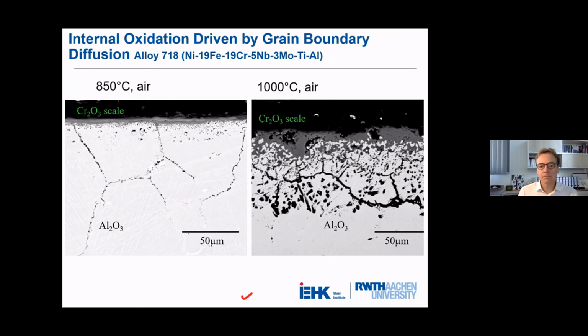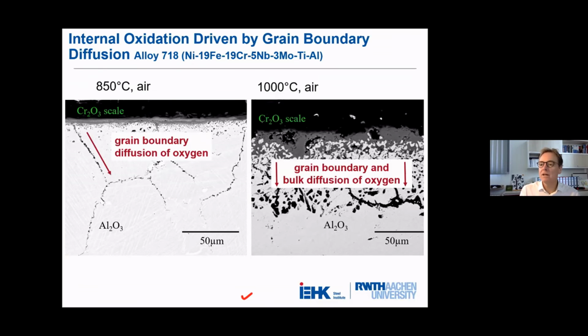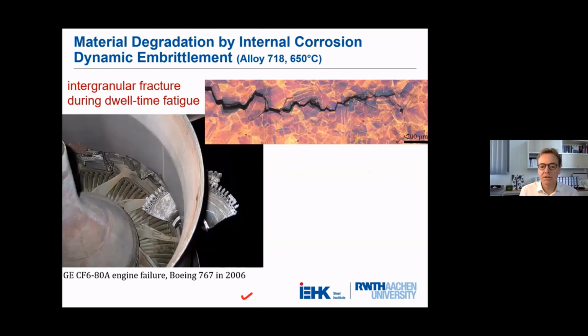And at even lower temperatures and fatigue loading with superimposed dwell times, there is a risk of oxygen diffusion-driven intergranular fracture. That is a failure of such a gas turbine disk, and that was due to intergranular failure. That is then an example of an experiment, and we see that the crack really follows the grain boundary.